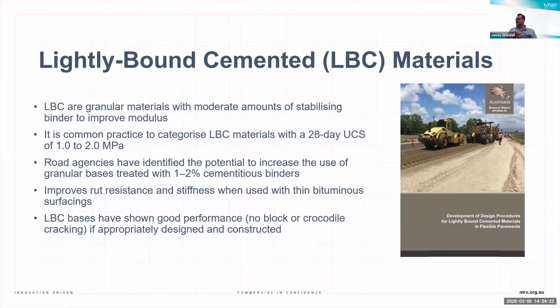But this next bit of work is just outlining some work we did through Austroads to look at what are called lightly bound cemented materials. Essentially what we're doing is stabilizing unbound granular materials with small amounts of cementitious binder, typically general blend cement, so a blend of general purpose or ordinary Portland cement with fly ash. And we're trying to get a 28-day UCS strength of between 1 and 2 MPa.